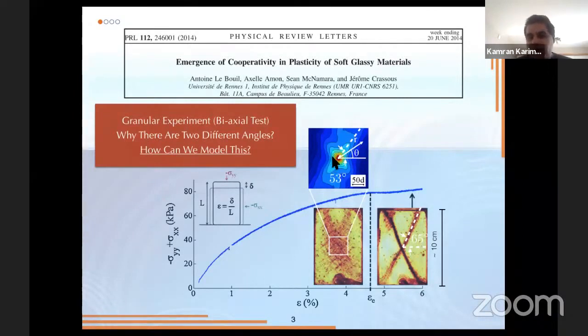So they also studied the correlation function, which is, if you sit at an active site and ask at what angle it's most likely to see the next event, the answer is given by this correlation function, and most likely at 53 degrees you can see that the next active event might occur. So surprisingly, the angle corresponding to the shear band was different than the angle associated with these precursors. And so our motivation was to understand this and develop some theoretical background to explain this difference in angles, and also reproduce their results by numerical simulations.